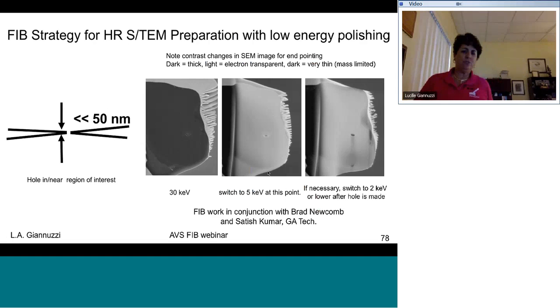Okay, so this was the work I showed you earlier with these carbon nanotube carbon structures. In this case, I only finished with 5 kV because this is all that I had on this older FIB. But what I like to do is use my 30 kV to endpoint and basically get it thin enough to make it core electron transparent. And this thickness is going to change for different materials, of course. And then at this point, I've switched to 5 kV FIB. What you see here is the contrast goes from dark to bright in the SEM image. The reason it goes bright is because you're getting secondary electrons off the front surface as well as the back surface. And then you're going to get to a point where the contrast goes dark again. When the contrast goes dark again, now you're mass limited.